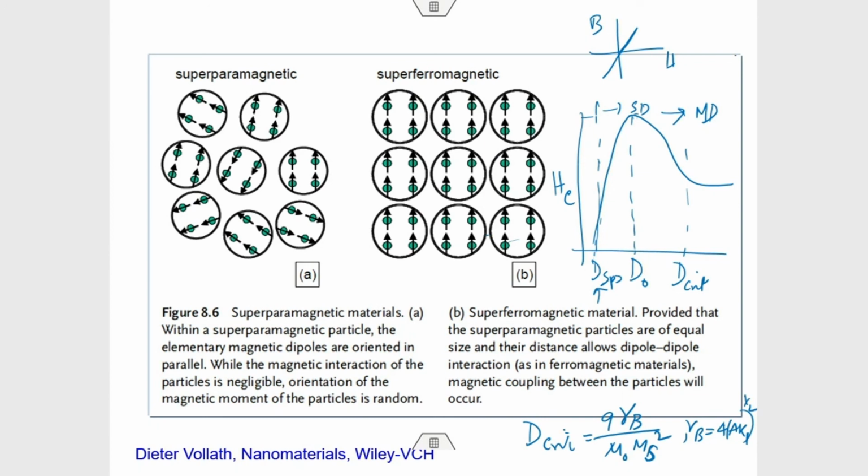For iron, nickel, cobalt that are mostly nanocrystalline, not amorphous, with about 10 to 15 nanometers grain size, practically no hysteresis loop is shown. So from a technical point of view, if the idea is to fabricate a strong permanent magnet, coercive force should be as high as possible. These cannot be used for that, but they can be used for switching operations, because with no hysteresis loop there is no loss of energy. So you would like to utilize the superparamagnetic effect in switches.